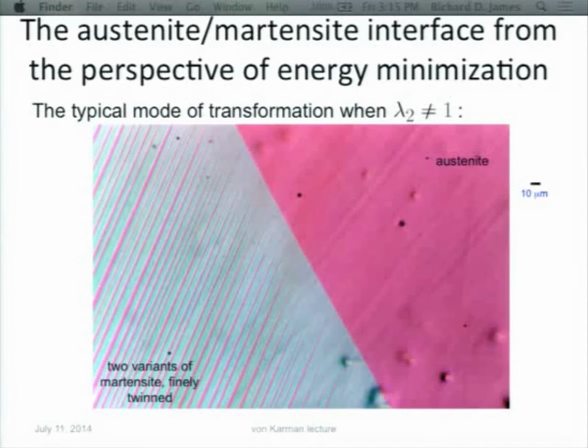Okay. Now, I'm approaching this fourth idea about hysteresis. This is what we see in many crystals which undergo reversible or semi-reversible phase transformations. It's widely observed. It happens when the middle eigenvalue of that transformation stretch matrix is not equal to 1. And it says that the austenite phase, the cubic phase, this picture was taken in a single crystal, but it happens in a more complex way at the finest level in polycrystals as well.